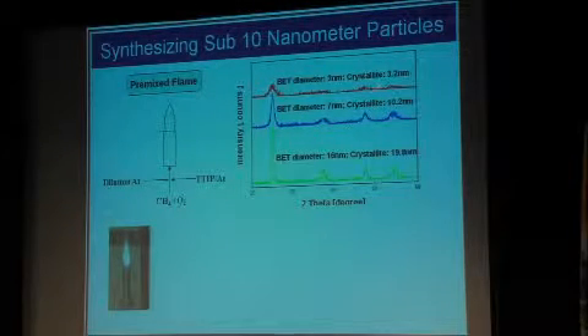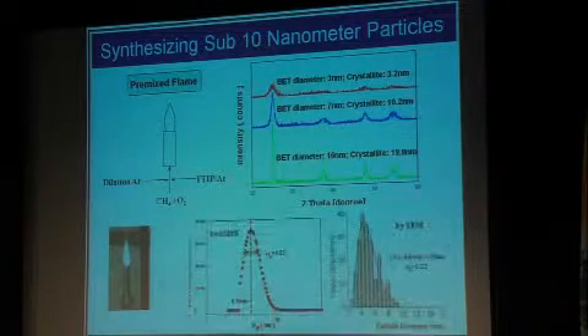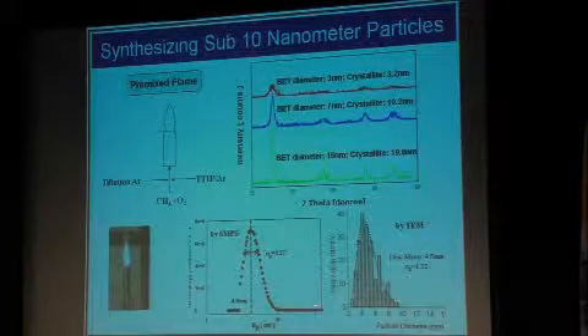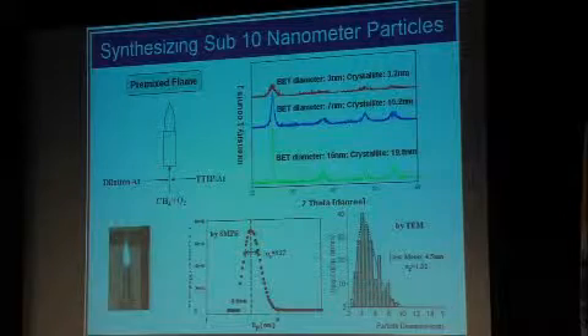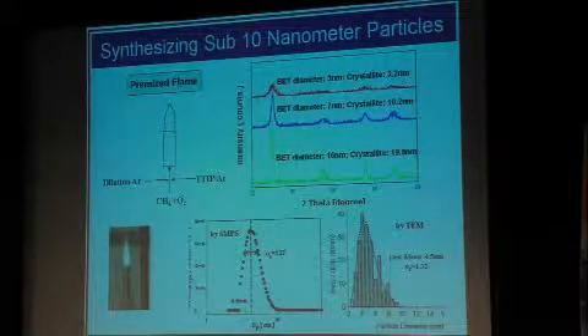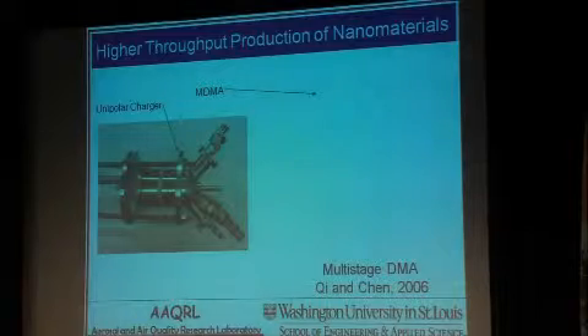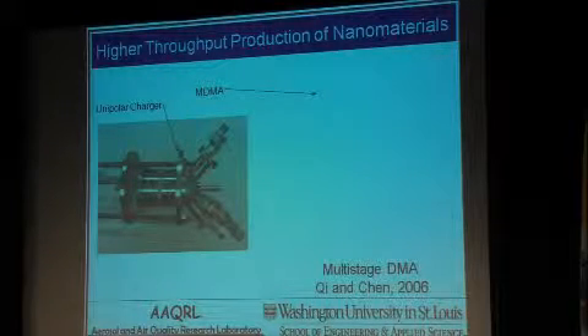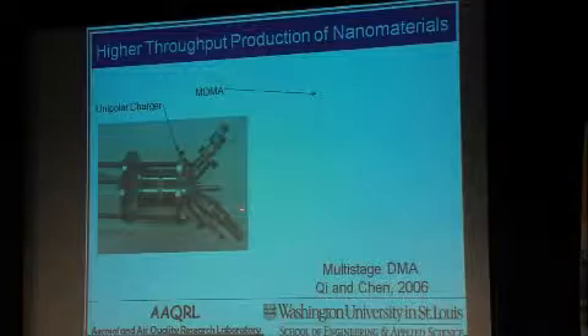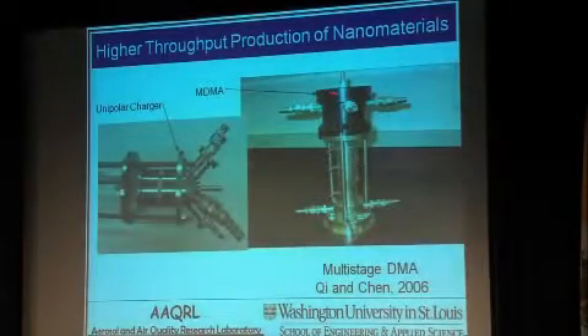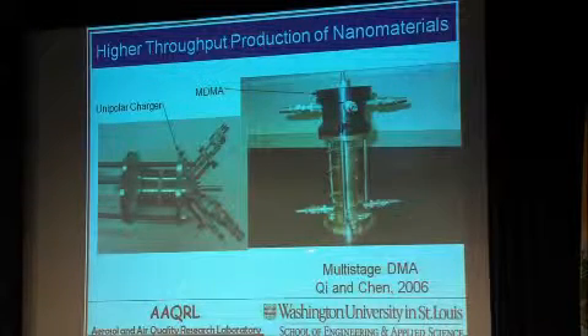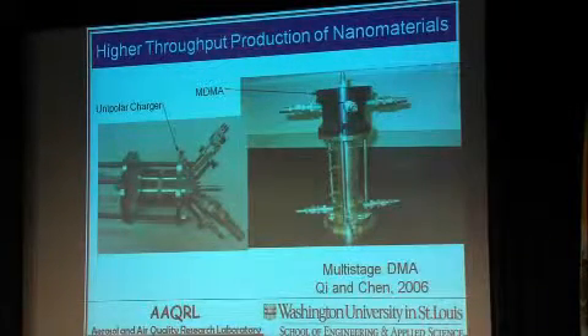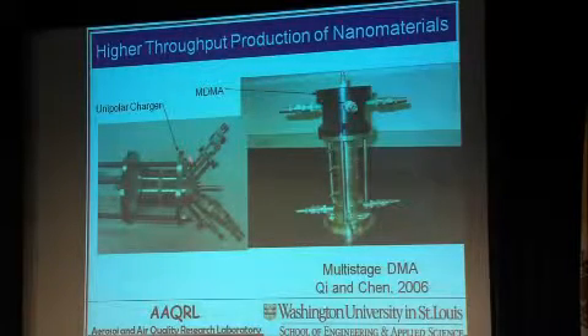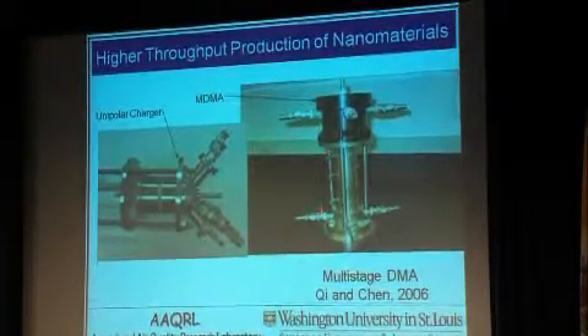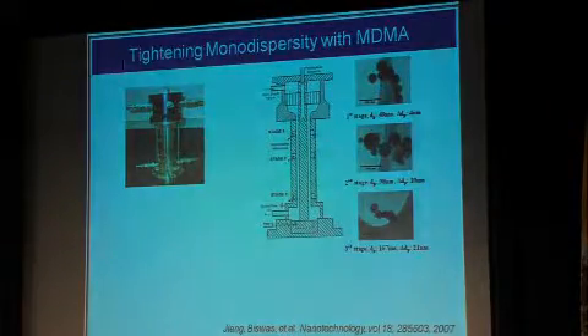You can see we make very tiny particles. And again, you can see the distribution of the size. And there is, of course, certain spread, but the mean size here is about 4.6 nanometers. Then we bring tools into play. My colleagues at Washington University have designed these tools. These basically bring in the aerosol, place a charge, use an electrical field. So it's called a multi-stage differential mobility analyzer. And what this allows me to do is very effectively charge the particles and then classify them and make them into a narrower size distribution.